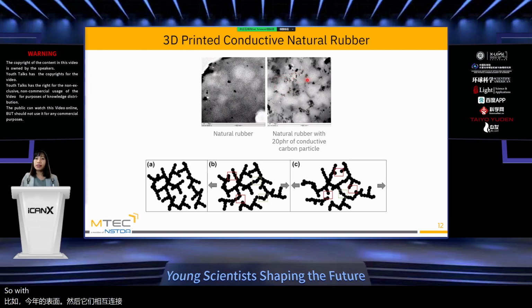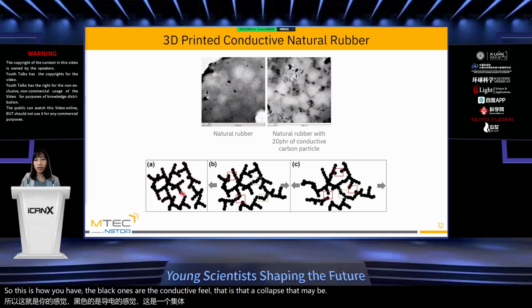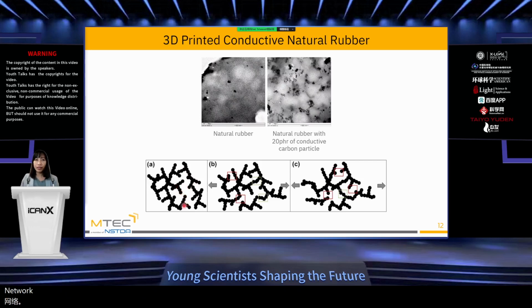With this in mind, imagine that you have this material that has rods connected together, and then you have the electrons that will be able to travel. What we could do with that material, based on this fundamental, imagine if you look at the picture at the bottom. Picture A is the original state of your material. The black ones are the conductive fillers that are connected, making a very good network for the electrons to travel.